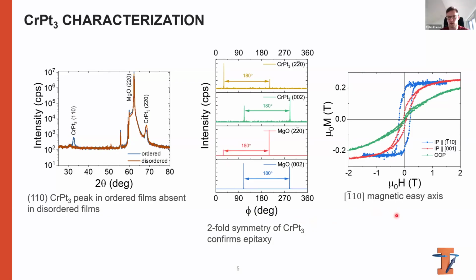Finally, we looked at the magnetization. We did magnetometry measurements, and we see that we have the magnetic easy axis along the 1 bar 1 0 direction, which is in plane for our 110 oriented chromium-platinum-3. We also see a relatively large coercive field on the order of 0.3 Tesla.